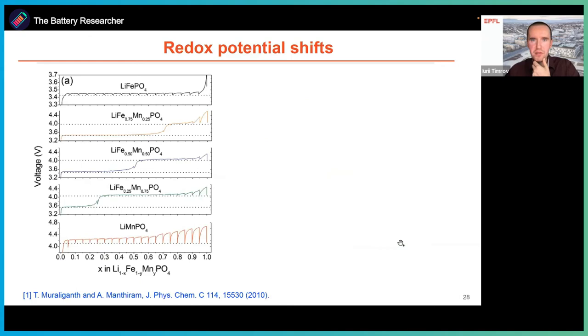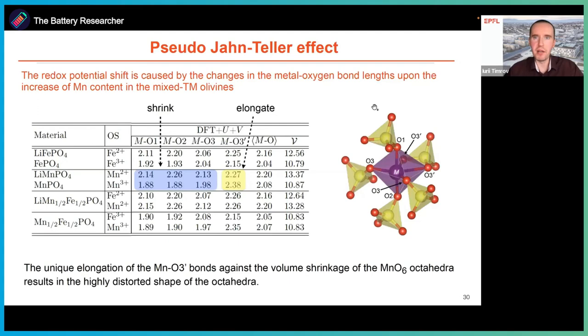In the literature, there are several papers explaining why this is happening. And this is happening because there are changes in the metal-oxygen bond length upon increase of manganese content in the mixed transition metal olivines. So in this table, I report the bond length.